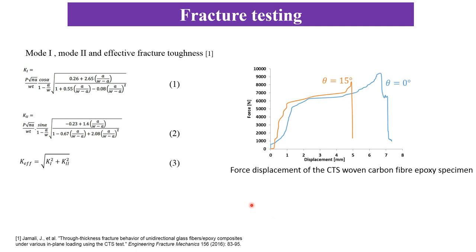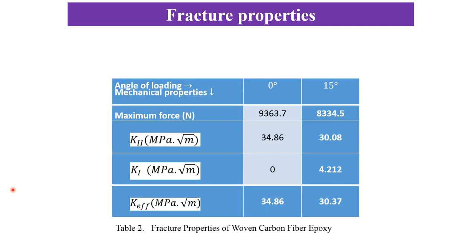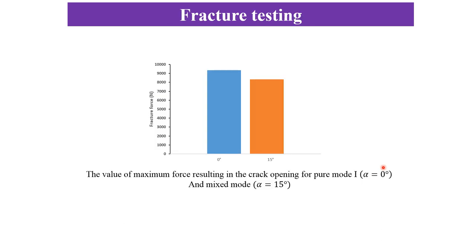To calculate the value of fracture toughness, mode 1 and mode 2, and effective fracture toughness can be calculated using these relations. The calculated value of the stress intensity factor of fracture toughness is shown here, pure mode 1, mode 1 and mode 2 components, and here is the effective value of the stress intensity factor for 0 degree and 15 degree loading angle. The maximum force, the force at which the crack opens, are compared here in this picture. So there's a little bit of drop at 15 degree compared to the 0 degree mode of loading.